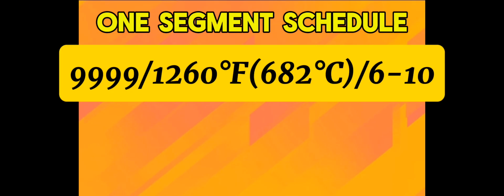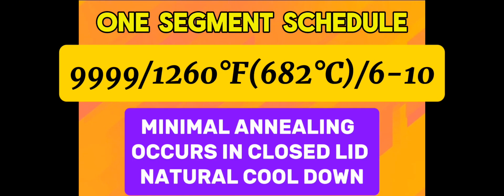Fire the stringers using this one-segment schedule: 9999 to 1260 degrees Fahrenheit or 682 degrees Celsius, for 6 to 10 minutes. Some will note the absence of the annealing segment. Small pieces of fused glass generally do not require annealing. The required annealing is minimal and will occur in the closed lid natural cool down.